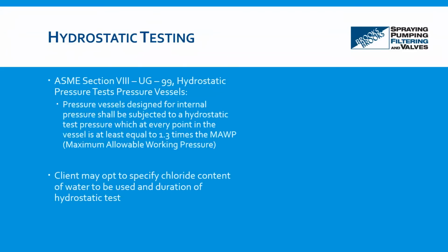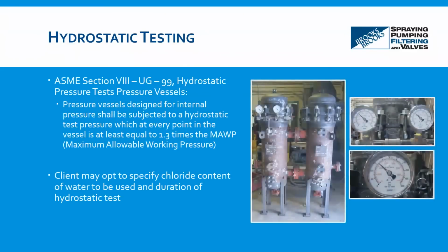So hydrostatic testing, by code, the test pressure is to be at least 1.3 times the maximum allowable working pressure. You're going to be using water, and there could be situations, in fact, where the client may require the water to have a maximum chloride content. Normally city water is used to test the vessel. So if that water has a higher chloride content than what is acceptable by the customer, the fabricator would have to bring in water from a third party.